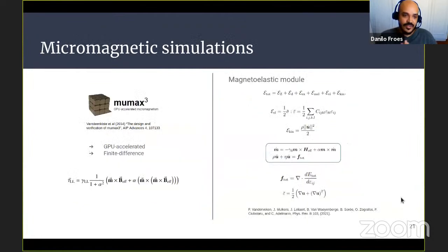And for the micromagnetic simulations, we implemented the MuMax3 software, which solves the Landau-Lifshitz-Gilbert torque equation and the energy minimization. The different thing here is that we employed the magnetoelastic module of MuMax, which is very novel. It's been out since the end of last year, the end of 2020, and it includes the elastic, kinetic and magnetoelastic energies. It solves the coupled equations: the Landau-Lifshitz-Gilbert equation, but also coupled to it, the elastic equation of motion. So all of these are solved coupled in this module.